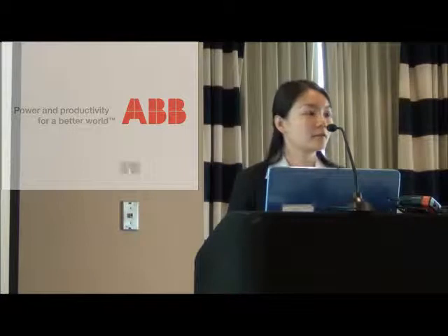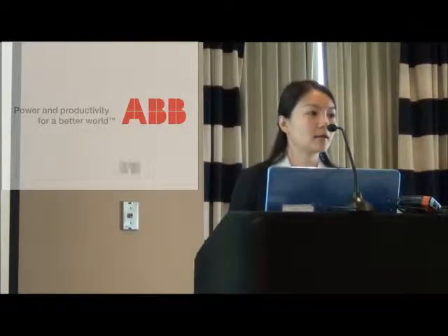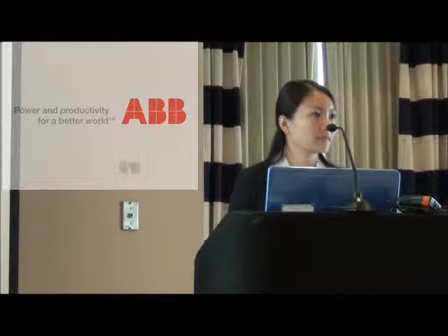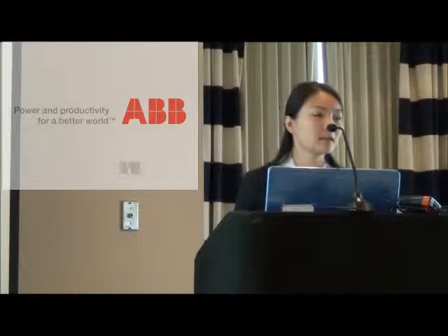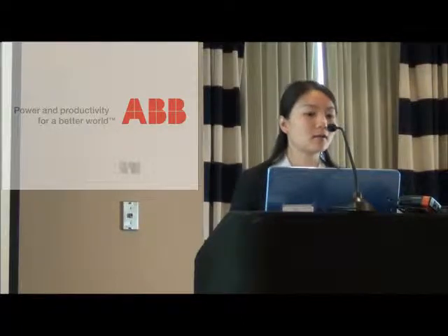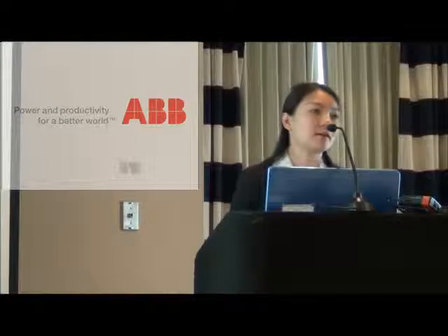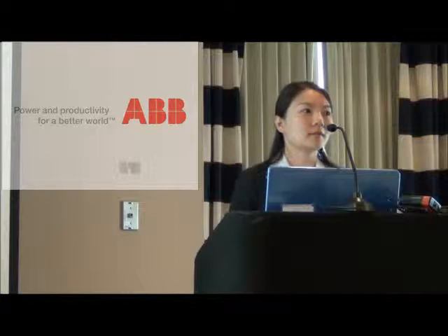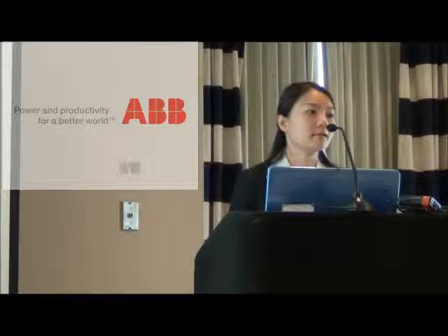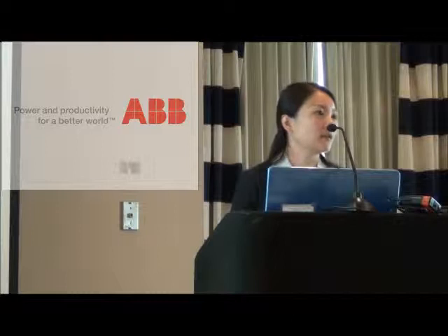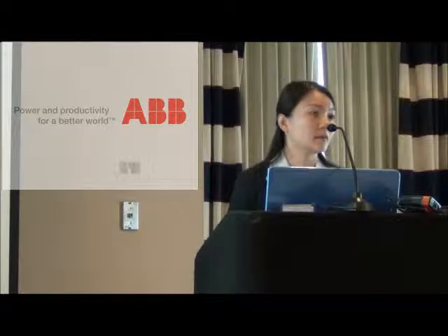Regarding the thermal conductivity, we are using a hot disk equipment. It was from Sweden, and now it's kind of standardized, but it's different from the IEC or ASTM standard. You use two sample blocks with a sensor in between, and by applying electric current, it heats up the sample on both sides, and then you measure the thermal conductivity.